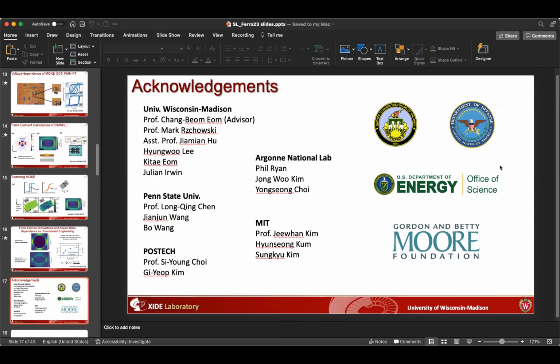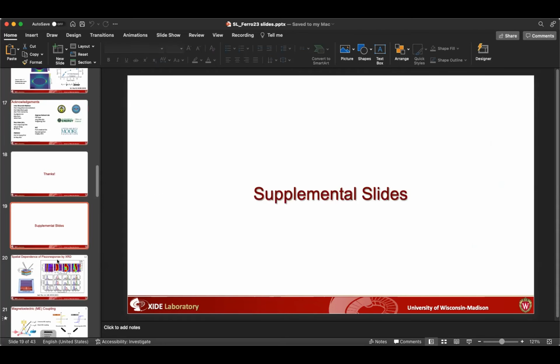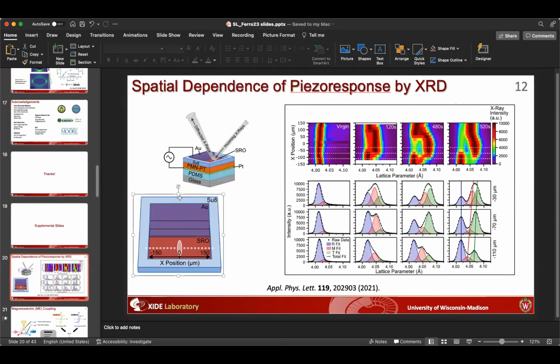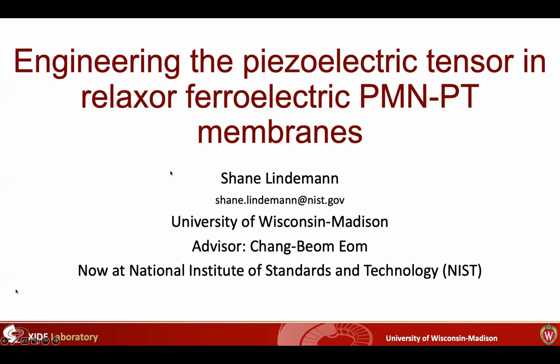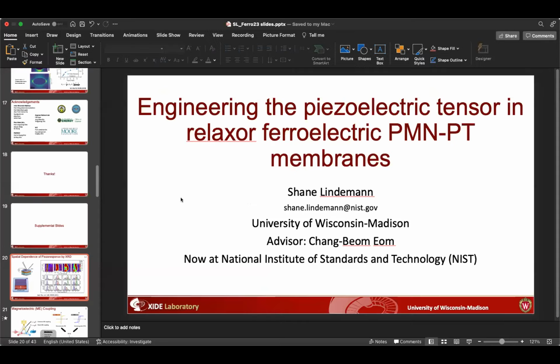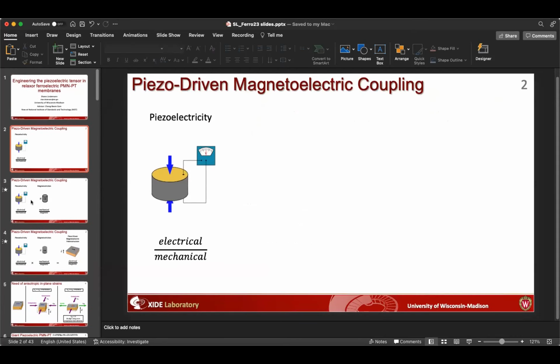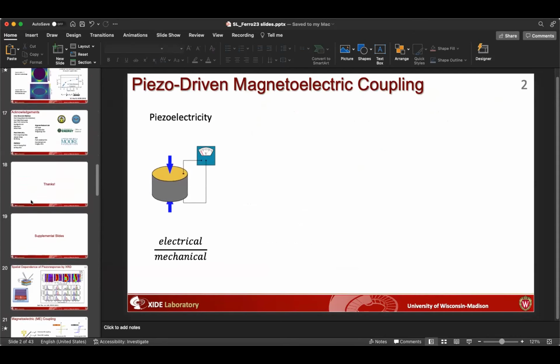The ferroelectric hysteresis. Also, can you explain the model of how you're thinking about it? So the domain state's actually pretty complicated. We did some synchrotron experiments where we tried to observe what the domain state was, and as grown, it was pretty uniformly rhombohedral with a little bit of monoclinic phase.